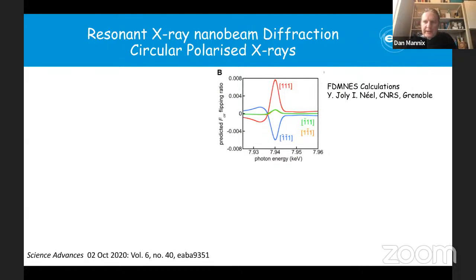Now, what we wanted to test was whether these contrasts that we're looking at are really associated with the resonant scattering and magnetic domains or not. One way to test this is with theoretical calculations. We have some theoretical calculations from Yves Joly at Institut Néel using his developed FDMNES code. He can predict the circular polarized flipping ratio. These are calculations of what we would expect for a domain aligned parallel to the beam direction, and this is one anti-parallel to the beam direction, but in the scattering plane. And these are the ones perpendicular, which with circular light have only a very small component, the vertical component sticking out of the film, much smaller than the ones in the scattering plane. That's what the theoretical calculations give.